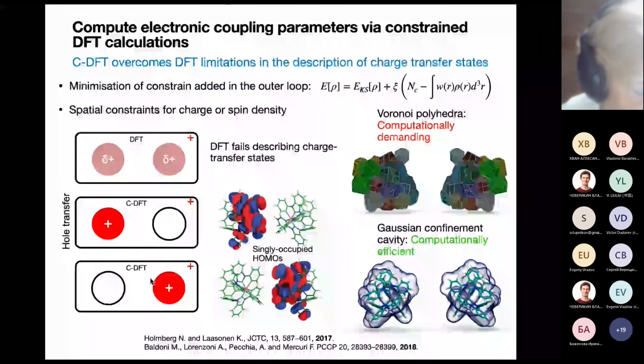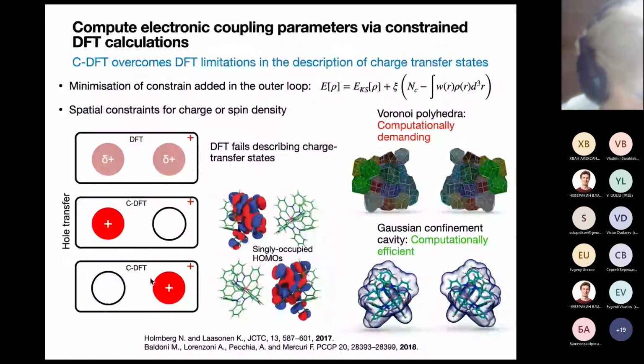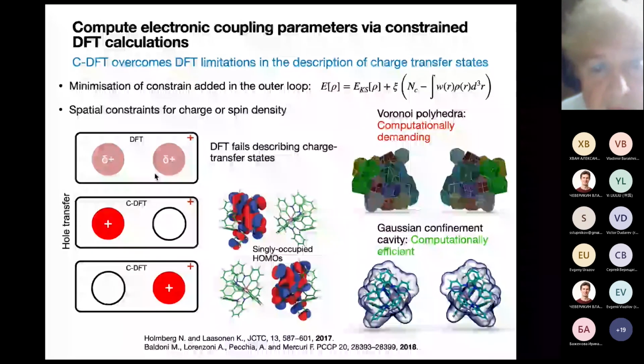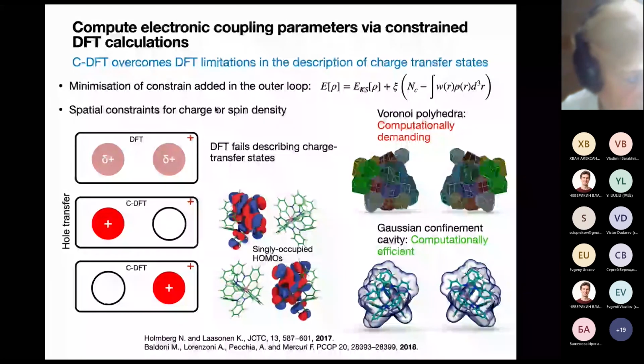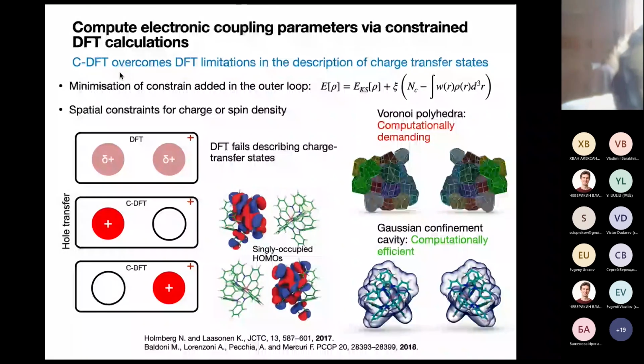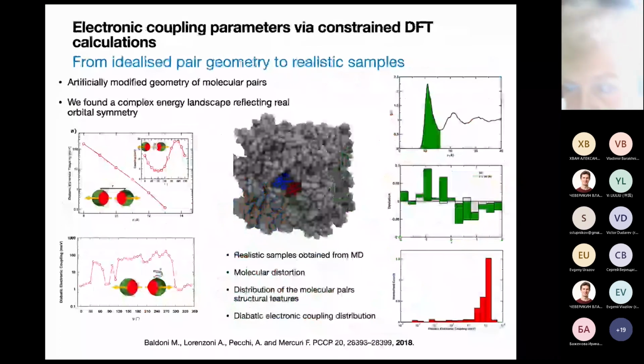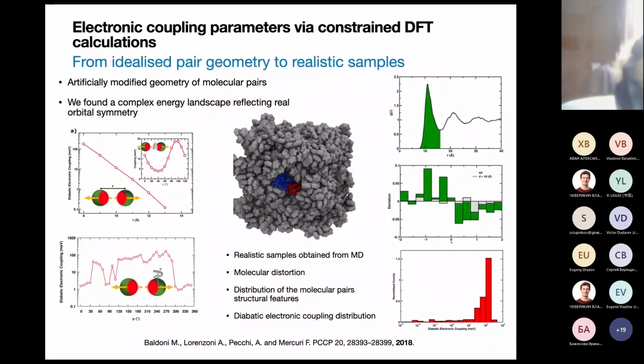So the point is that one will use density functional theory for this kind of calculation, but DFT fails in describing charge transfer states, giving as a result an average between the initial and the final state. We overcome this limitation using a different implementation of density functional theory, imposing some spatial constraint on the charge and spin density. So basically we can force the DFT to give us the right results in the two charge transfer states.